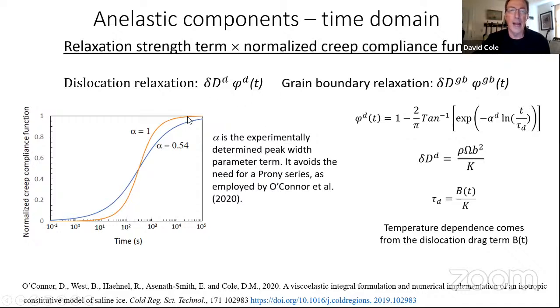At any rate, there are two things going on. One is how the process is realized as a function of time, governed by this normalized creep compliance function, and then how much strain you actually get out of that process, which is governed by this relaxation strength. Both the grain boundary and dislocation relaxation have a characteristic central relaxation time, determined by the kinetics of the process and temperature, and a strength. The strength for the dislocation process is a linear function of the dislocation density.